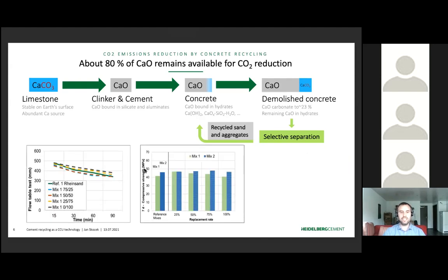As we remove these hydrates from the aggregates and the sand, what we receive are very high-grade recycled aggregates. They cannot be compared with the conventional ones. As a result, they can fully replace 100% of virgin materials, including the sand fraction, which is not possible with common technologies. And we can do that without sacrificing fresh concrete properties, as you see in the left graph, and also without sacrificing the strength of the concrete, as you see on the right graph. And this is not just for some low-grade concrete. This is valid for conventional structural concrete with 40-50 megapascal compressive strength. This is also done without any adjustments to the mix design of the concrete, so one does not need more cement or more admixtures.